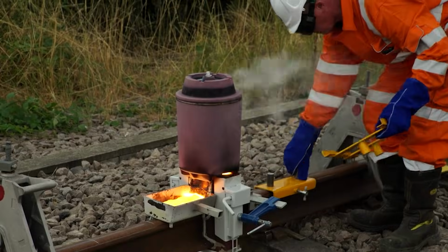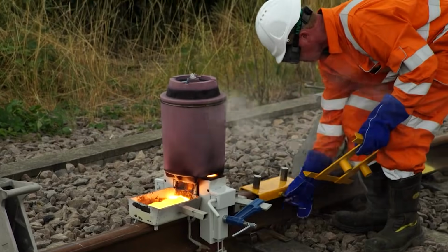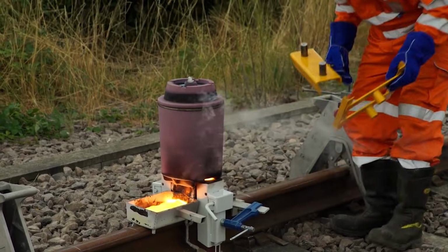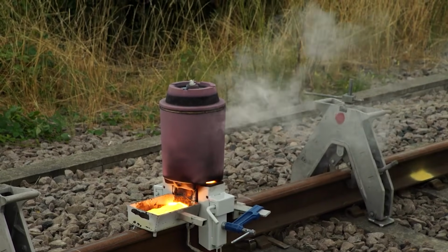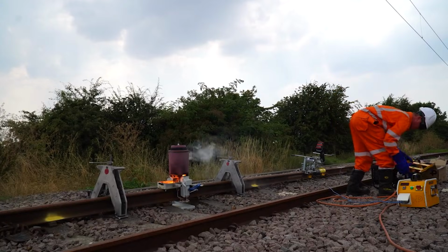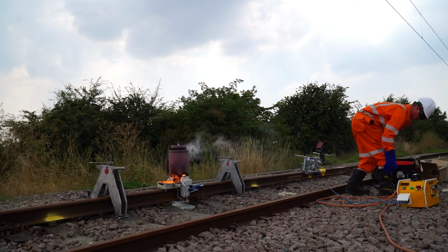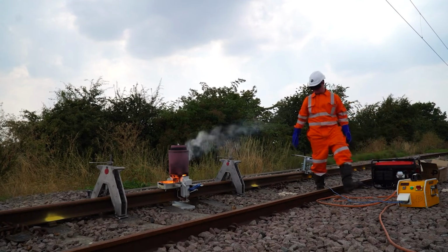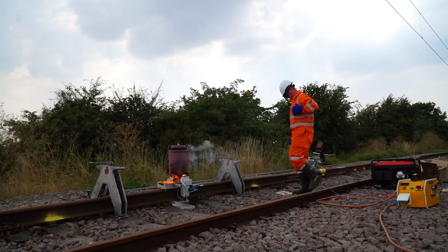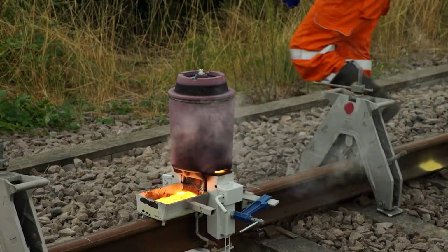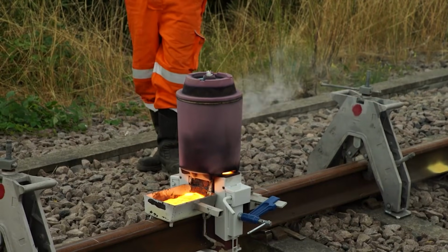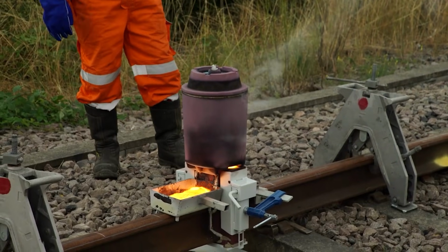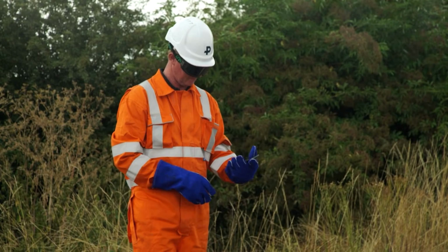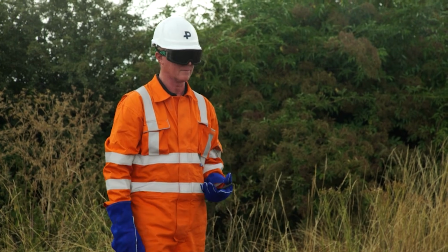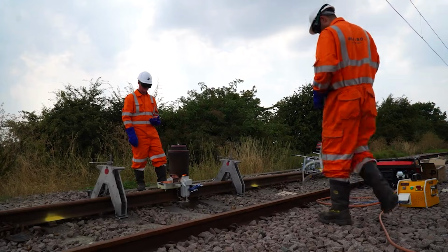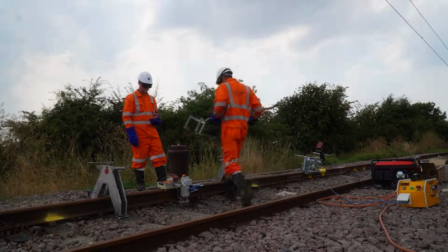As it flows in, it fuses with the rail ends, allowing limited diffusion of carbon and alloying elements to ensure metallurgical compatibility with the parent rail. The mould fills from the bottom up, forcing air and the slag up into the riser and preventing trapped gas or inclusions in the joint. Every portion is manufactured under controlled conditions, meaning that what happens next is predictable. That's the power of aluminothermic welding. It's a portable foundry chemistry refined for trackside use.